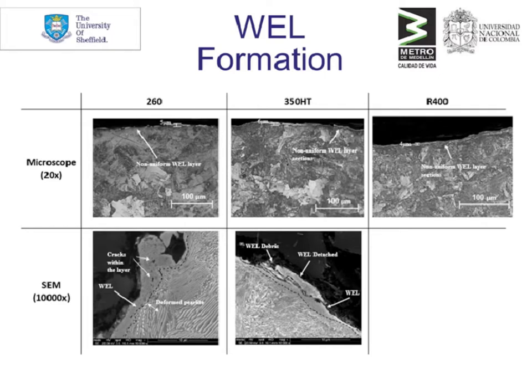Here you can see some analysis on different rail grades. We get very different forms and levels of white etching layer under the same grinding conditions and different rail grades. Very important to try and understand this as more premium grade rails are being used at the moment. We need to understand how they can be ground in the most effective way.